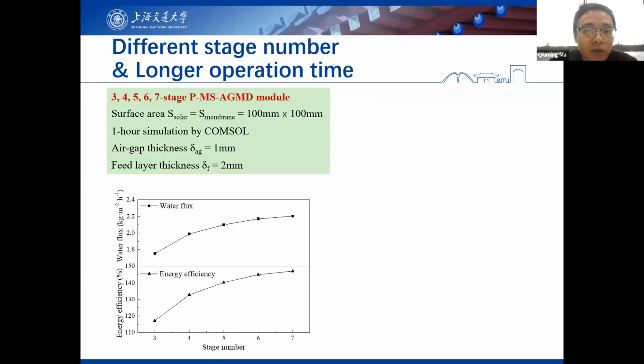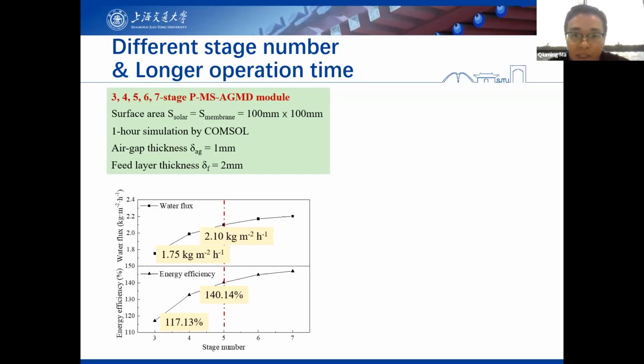And then we tried different stage numbers, and we tried longer operational time in simulation. And for different stage numbers, we tried up to 7 stages. And clearly the performance were better with the larger stage numbers. But we found that actually after stage number 5, the enhancement were limited. And at stage number 5, actually the energy efficiency could reach 140% with impressive productivity.